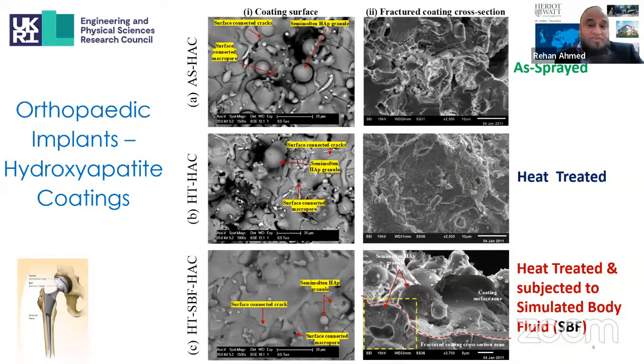This slide shows the surface morphology of hydroxyapatite coatings in the as-sprayed, heat-treated, and coating subjected to simulated body fluid environment. So the SBF, or the simulated body fluid environment, is used to ascertain coating response in the bioenvironment, and significant changes can be observed on the surface of these coatings in these conditions. And these changes also influence the residual stress profile in these coatings as shown in the next slide.